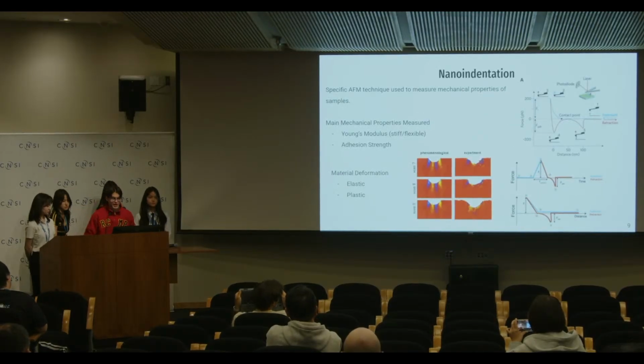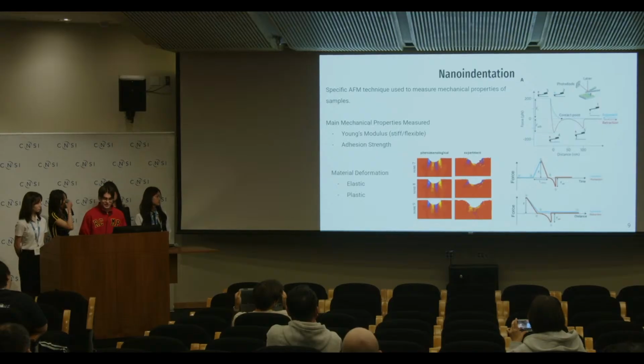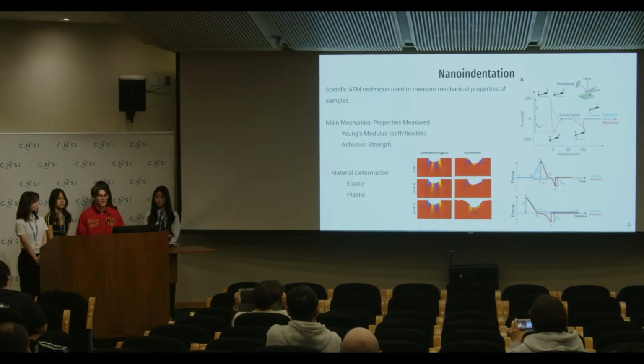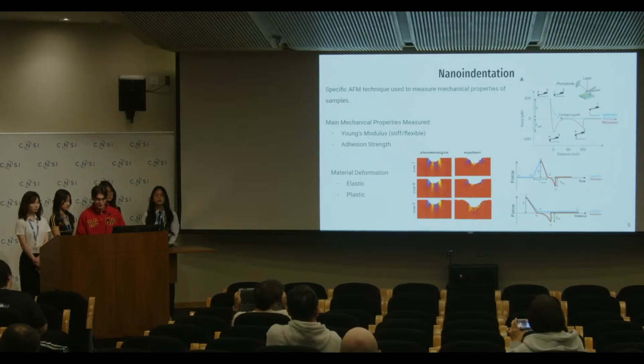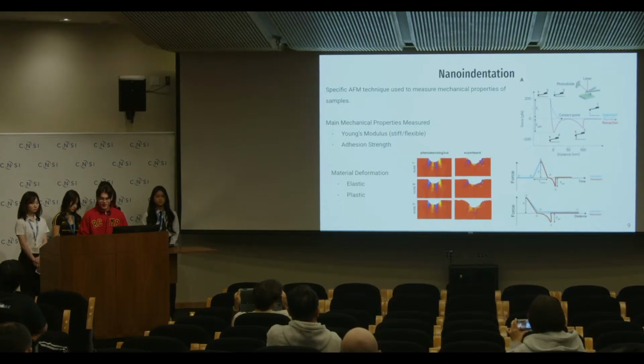So what is nanoindentation? Nanoindentation is a specific AFM technique that is used to measure the mechanical properties of your sample. You pretty much take the AFM and you press the probe onto the surface of your sample to feel around, and the force is measured by tracking how much the cantilever bends, and then you can also measure indentation depth, which is how far the tip goes into the material without breaking the sample.